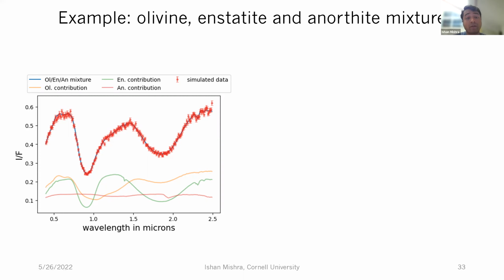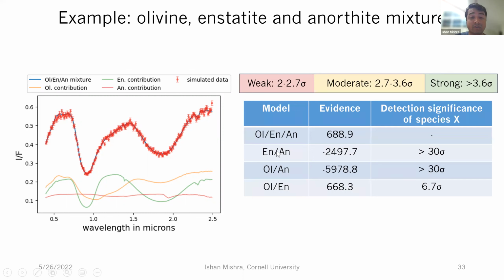So when we do our systematic analysis, basically we first start with a model that has all our candidates. So we say that, okay, we are seeing a big enstatite feature here. We are seeing an olivine feature over here, and so we just pick our candidates, and anorthite feature is not clearly visible, but there's a small dip here. So we pick our candidates, we do our analysis, we get some metric for the evidence for this model. Then we systematically knock them out one at a time.